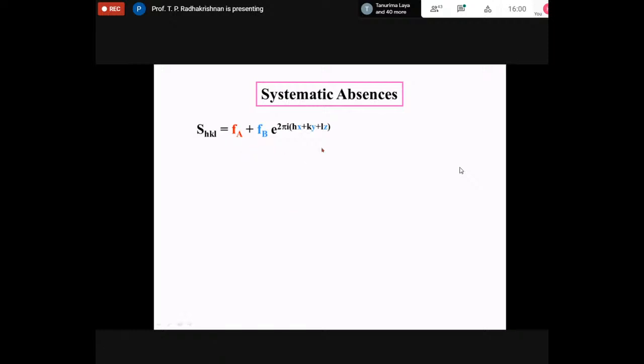So now let me explain why that structure factor looks like a very complicated equation and so on. And I told you phase and the atomic scattering factor, various terminologies. Now, that is actually what is used in crystallography. But to illustrate the meaning of this, I will relate it to the idea of systematic absence. So the two mysteries that I skipped earlier, for example, in a BCC lattice, H plus K plus L has to be even. If it is odd, you will not see an intensity. Why? The answer comes by an analysis of the structure factor.